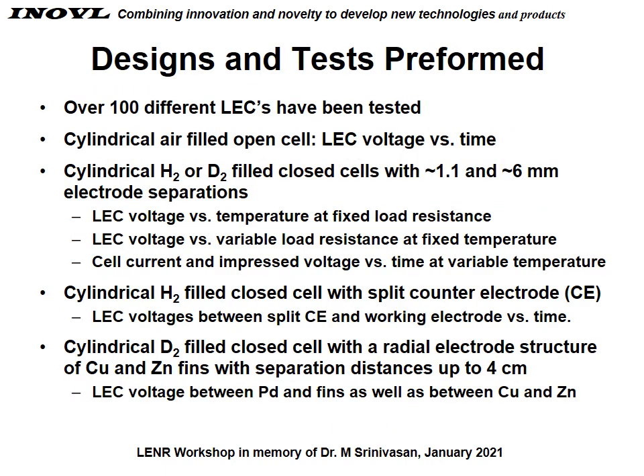So far, we've designed and tested over 100 different LECs. They include cylindrical air-filled open cell, where we did LEC voltage versus time, cylindrical hydrogen or deuterium-filled closed cells with both about 1.1 millimeter and 6 millimeter electrode separations, LEC voltage versus temperature at fixed load resistance, LEC voltage versus variable load resistance at fixed temperatures, cell current and impressed voltage versus time at variable temperatures, cylindrical hydrogen-filled closed cell with a split counter electrode, LEC voltages between the two counter electrodes,